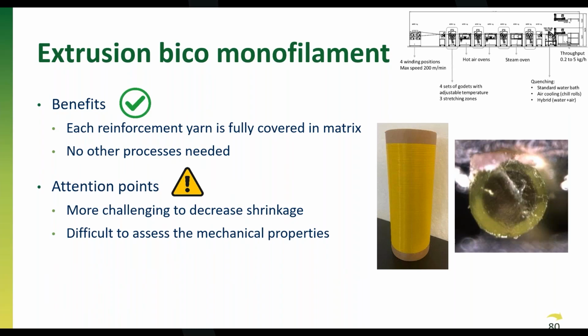Some attention points, of course, you're working with materials with different melting points. So drawing, but also decreasing the shrinkage are more challenging because you don't want to melt your matrix material during the process of forming the yarn. So there it's more challenging to decrease the shrinkage because you cannot do a relaxation at a very high temperature that is needed for the reinforcement yarn. Especially with the PCL, which has a very low melting point, it's even more challenging than with some types of PLA, where you are already a little bit closer to the melting point of also the reinforcement yarn.